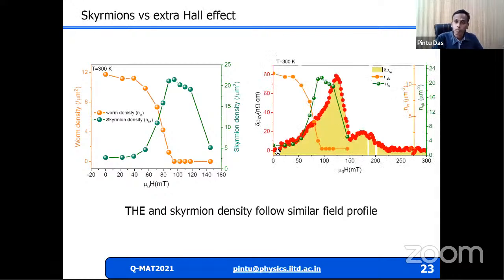So if we plot together with the topological Hall effect or the extra Hall effect, we are a little bit careful at this point because this is just our recent data. We have not yet understood fully. So we are saying extra Hall effect in this case. This extra Hall effect that we are measuring has an almost similar field profile as the skyrmion field profile. So we kind of show that this is related to the skyrmion evolution in the system.